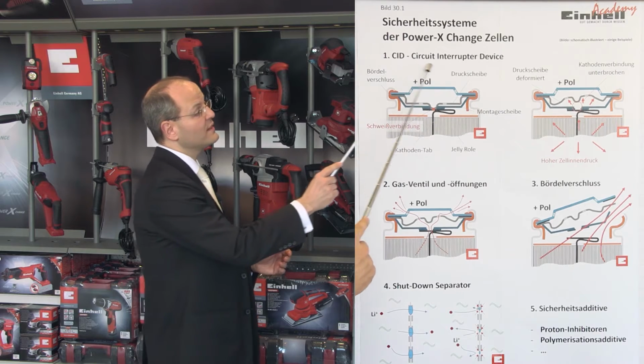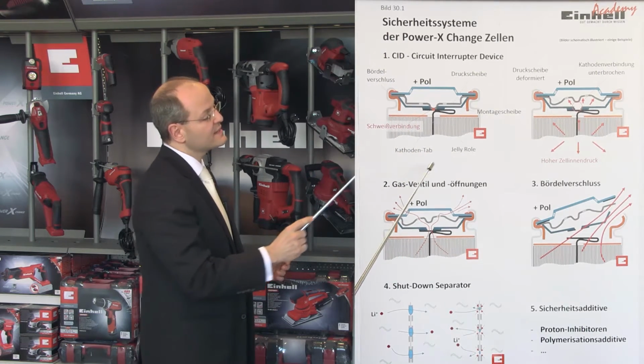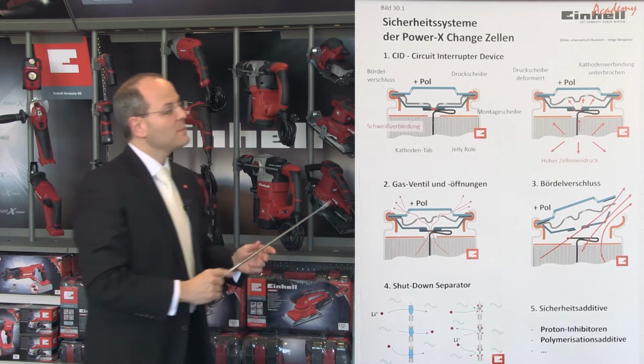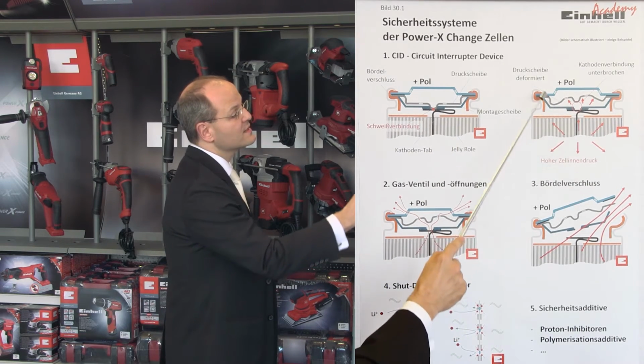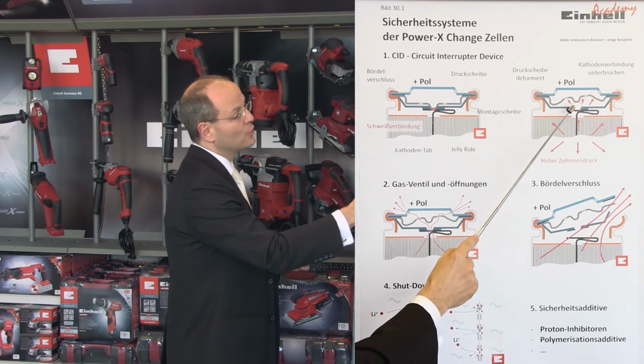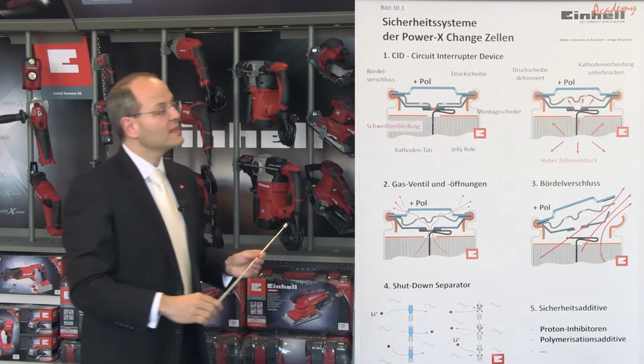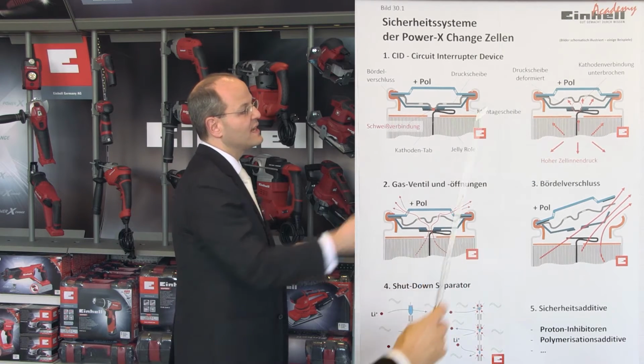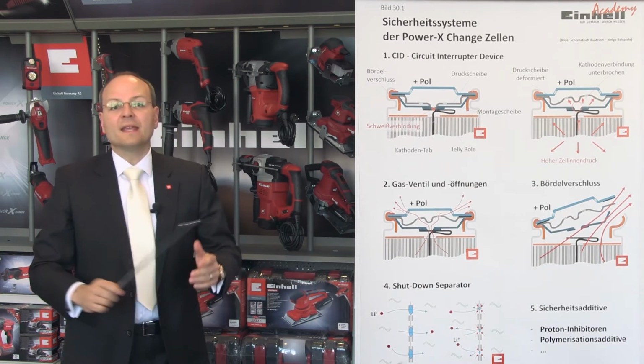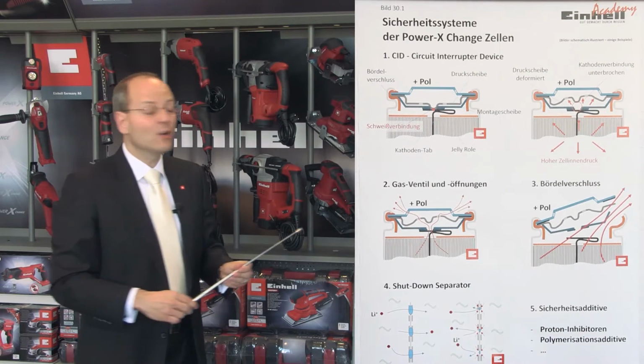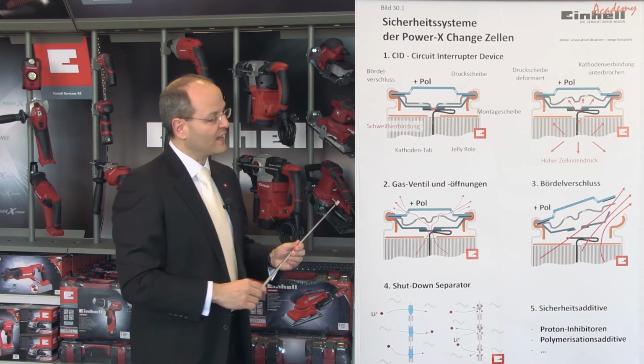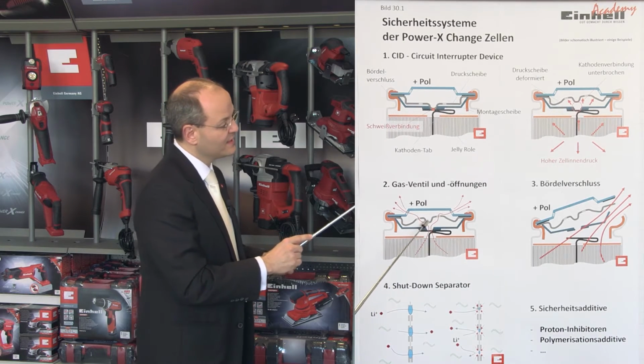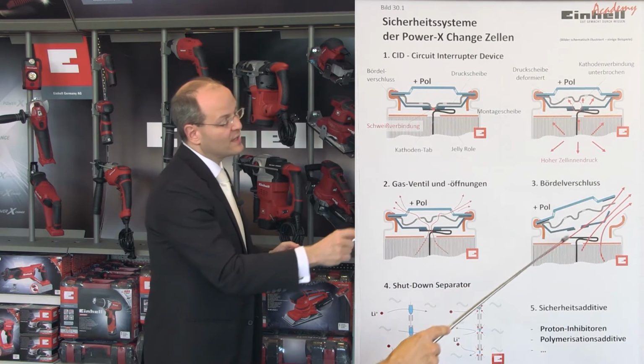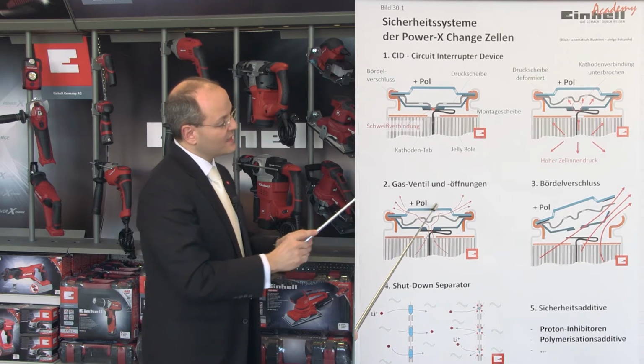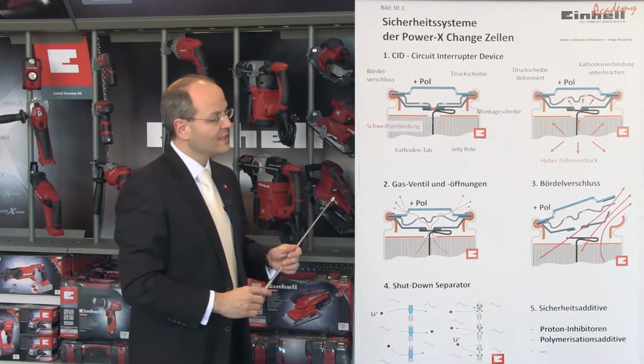For example, every cell has a so-called circuit interrupter device, CID, which monitors the internal cell pressure. Above a defined internal cell pressure, a so-called pressure disc deforms and disconnects the cathode connection to the positive pole. This interrupts all flow of current into and out of the cell. In addition, every cell also has two independent systems for controlled and part-controlled pressure reduction. These are the gas valves and the crimped closure, which acts as a predetermined breaking point. If the gas valves are unable to allow the gases to escape quickly enough, then the crimped closure opens.